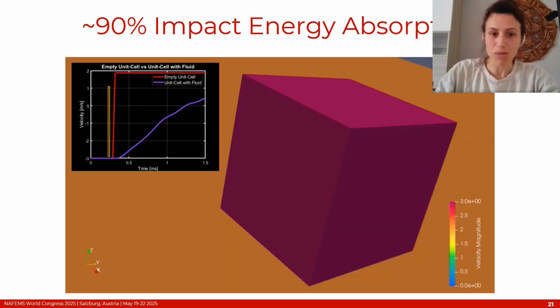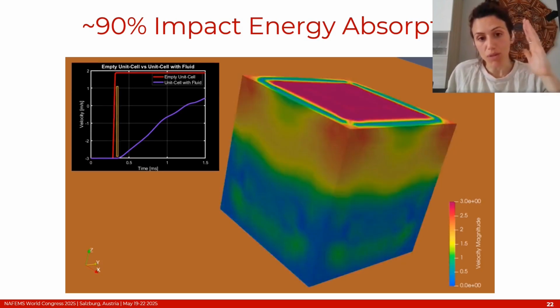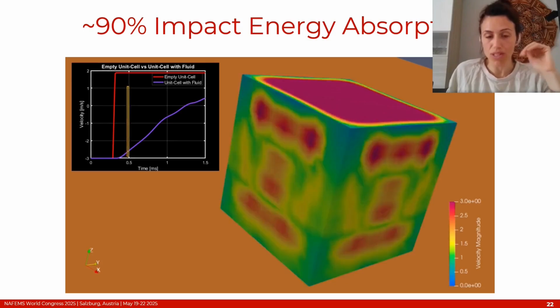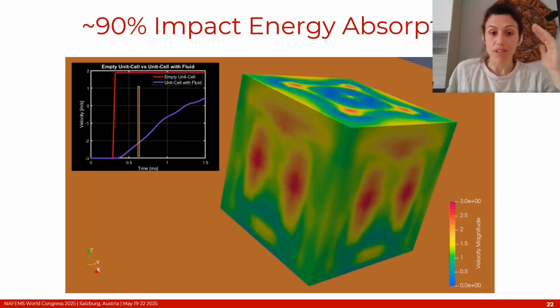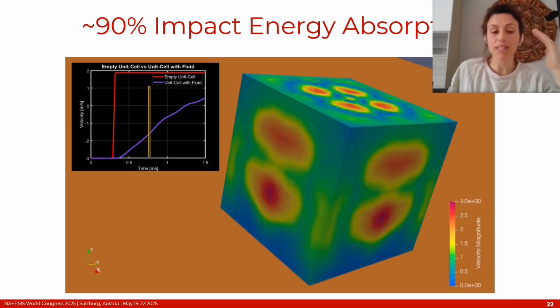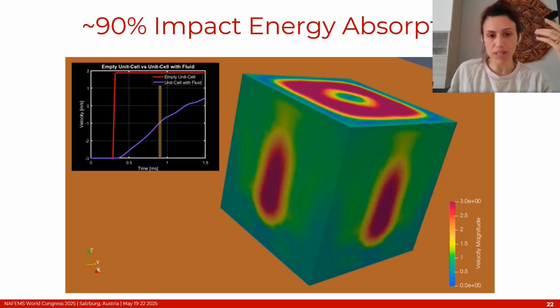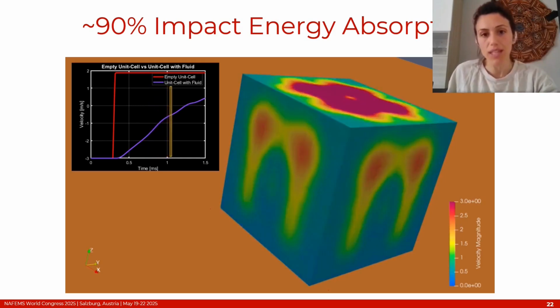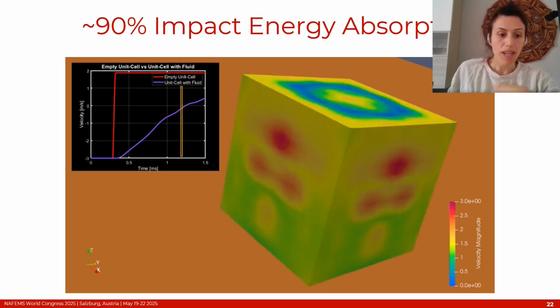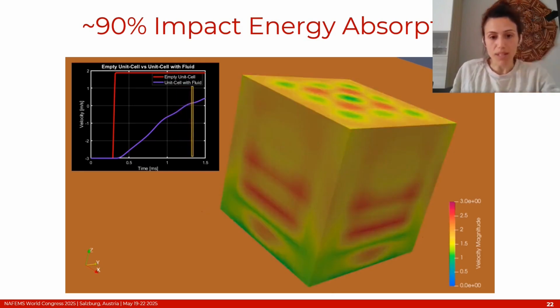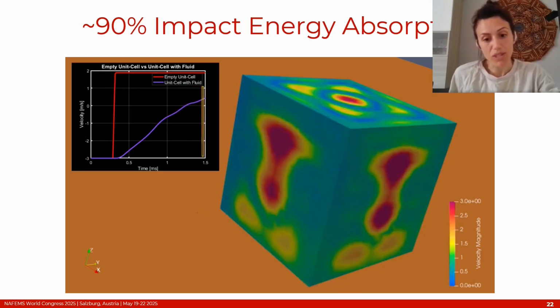In this movie, we see a simulation of this unit cell under impact. On the top left, we see the graph of the velocities, remembering that the slope of this curve, which is velocity versus time, is the acceleration. So the acceleration and then the force of the unit cell is much reduced, and a rough estimate would give at least 90% impact energy absorption. And this is a promising direction for designing protective materials with embedded damping properties.